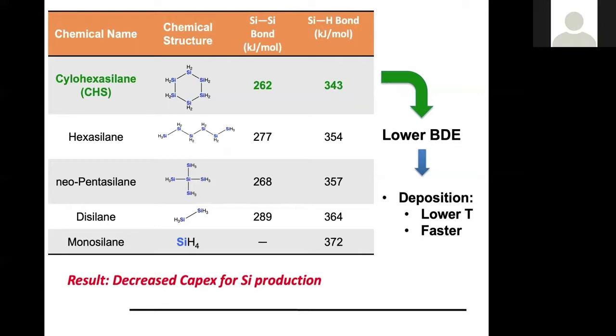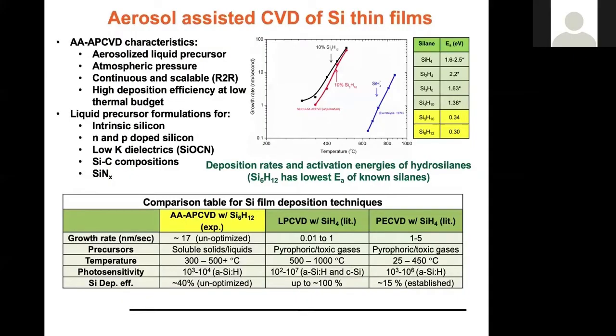Comparing it to the most traditional silicon precursor, monosilane, it requires a lot more energy to break those silicon-hydrogen bonds in monosilane. And that's one reason why CHS is superior: the bond energies are lower, and it gives much faster deposition rates. That deposition rate comparison is highlighted here in this slide, using a technique known as aerosol-assisted chemical vapor deposition.